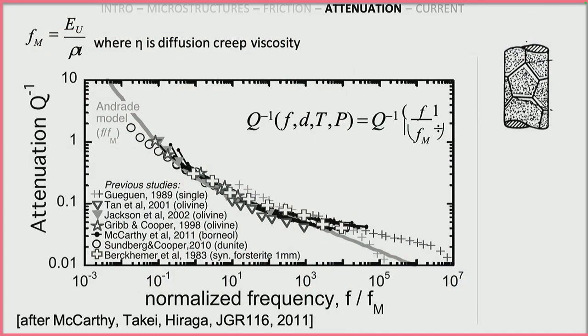So a study that I'm very proud about, it's very old, sorry, but I have to show it, is that I went to Japan. I was working on this novel material called borneol. It's just like mothballs, essentially, but it's really nice to work with in terms of like it has diffusion creep and dislocation creep, and you can really control the grain size and the temperature range. Again, that homologous temperature we talked about is very easy to obtain in the lab. And we got really beautiful data. It's the black data in the back that you can barely see.